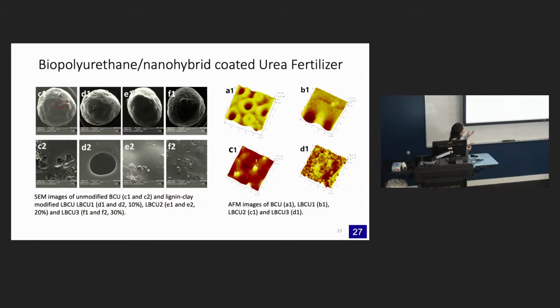Here are pictures with the nanohybrid. You can see we get a rough surface, and the pinholes get less and less. That's important, because if you can control the urea release, you can adjust your nutrients based on the plant growth period, and also reduce pollution. Nitrogen goes to the soil and water, and nitrous oxide affects the climate, resulting in serious global warming issues.